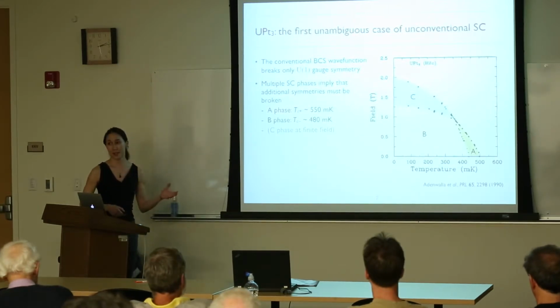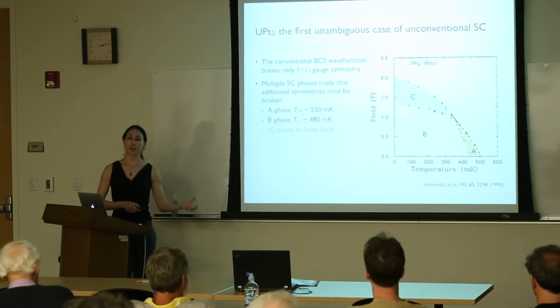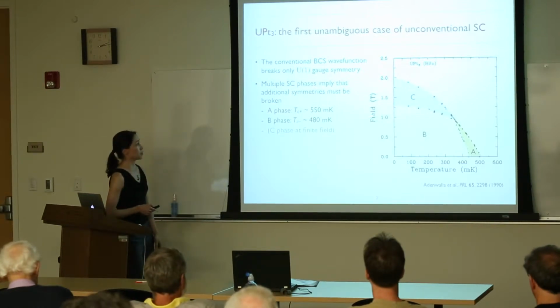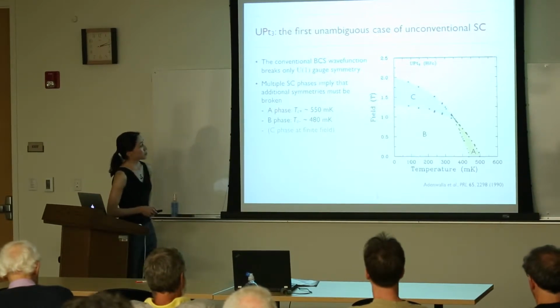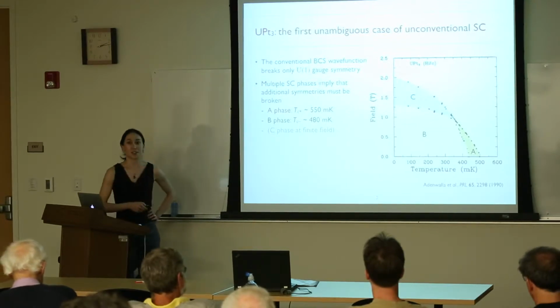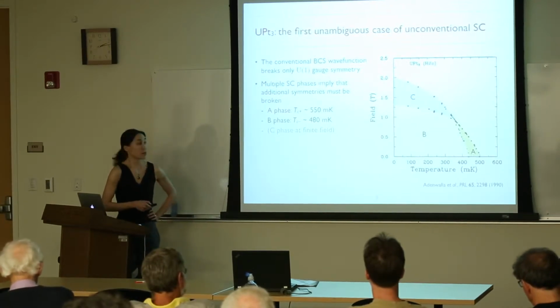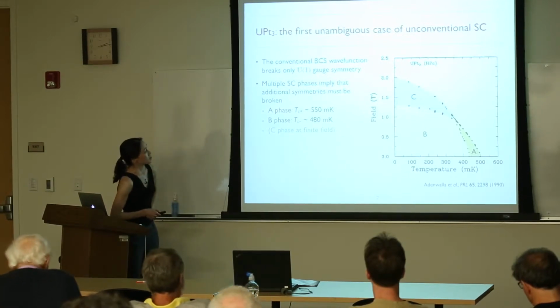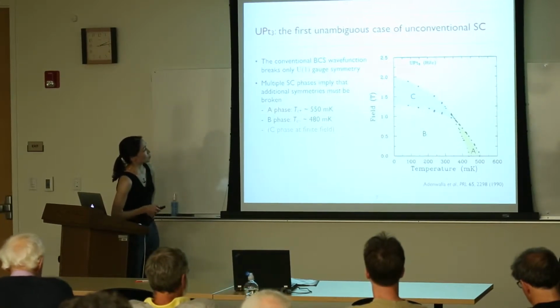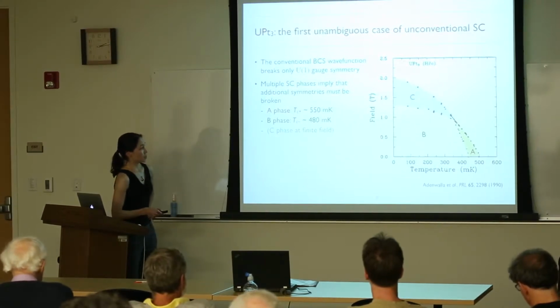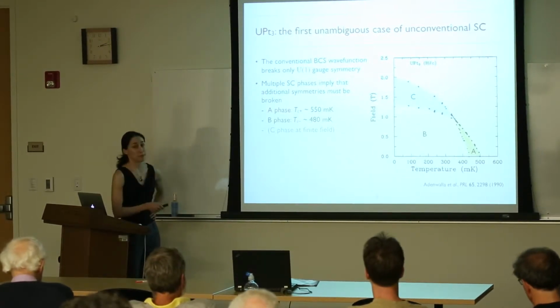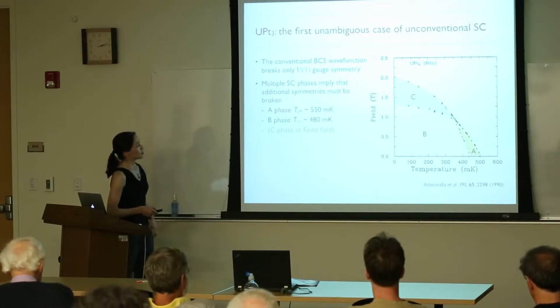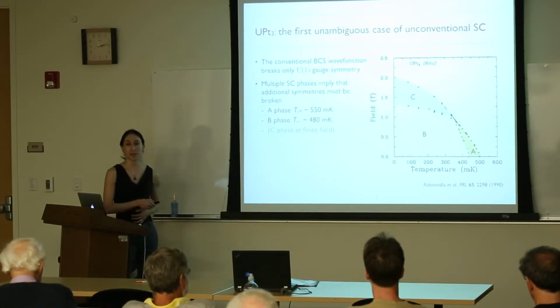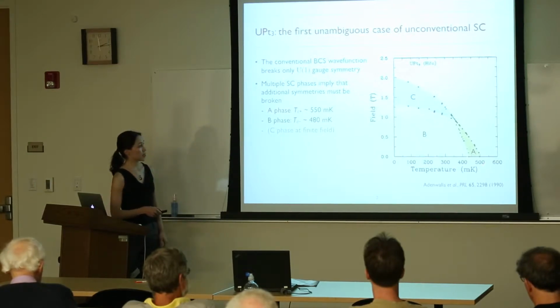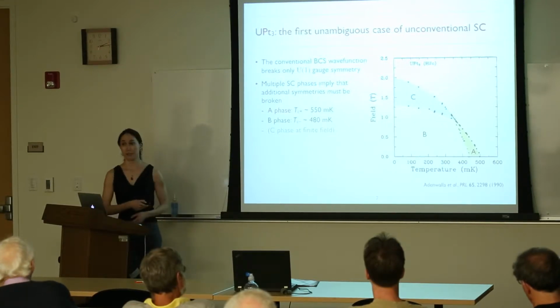But perhaps the most striking example that there was really more to be learned about superconductors came from uranium-platinum-3. I've shown the phase diagram here. This really changed the way that you would want to think about superconductors. What I'm showing is a phase diagram as a function of temperature and applied magnetic field. These data points are all indicators of thermodynamic phase transitions, one way or another. The point is that there's not just one superconducting phase, but three. At low fields, there's a high temperature A phase, a low temperature B phase, and then at finite fields, there's the C phase.